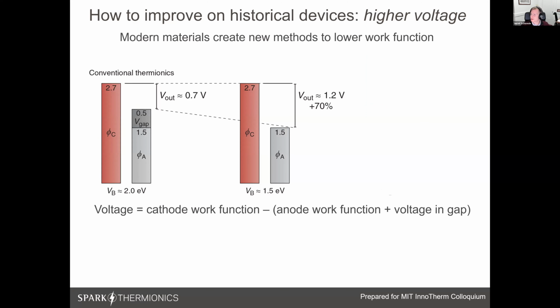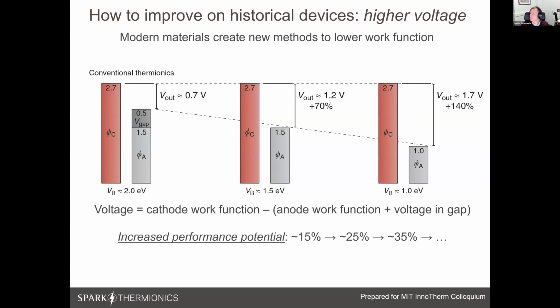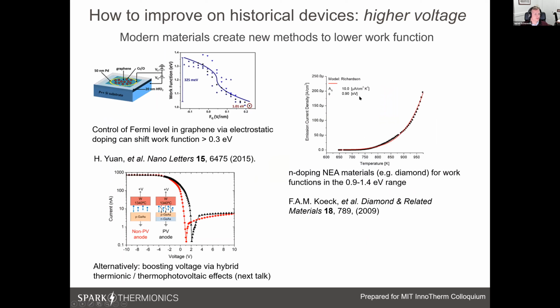But of course, we're not limited to chunks of refractory metal with coatings. There's several decades of materials innovation that we now believe we can apply to this. And like I said, there's in principle no known reason that we can't achieve this low work function of 0.5. And like I said, we have personally achieved 0.6. Of course, it's a very long road between that vacuum chamber demonstration and getting that stably into a device. And I'll just highlight a few of them here.